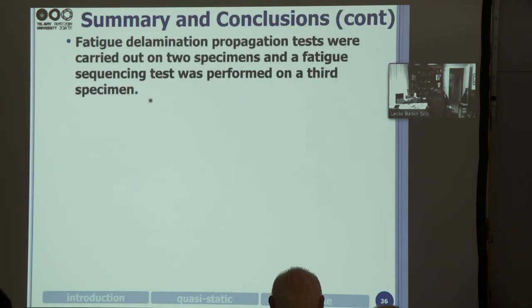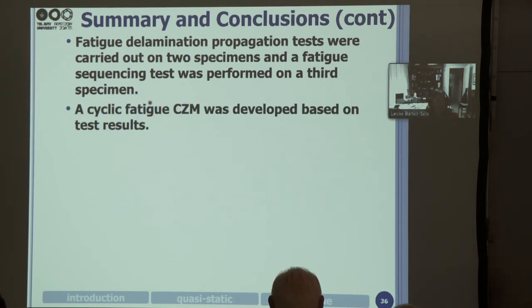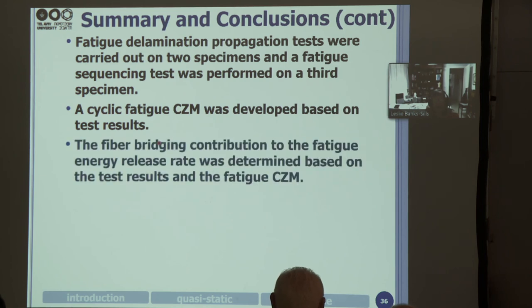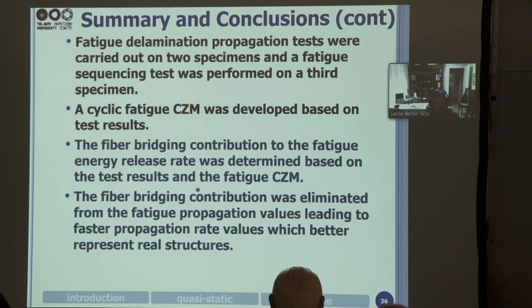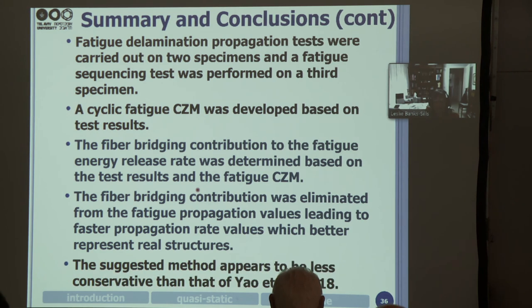And then we did similar work for fatigue delamination propagation tests. We carried out tests on 2 specimens at 3 million cycles, and 1 specimen with the fatigue sequencing testing that was suggested by Yao et al. And we obtained a cyclic fatigue cohesive zone model based on the test results. And the fiber bridging contribution to the fatigue energy release rate was determined based on the test results and the cohesive zone model in fatigue. The fiber bridging contribution was eliminated from the fatigue propagation values, leading to faster propagation rate values, which better represent real structures. And the suggested method appears to be less conservative than the Yao model from 2018.